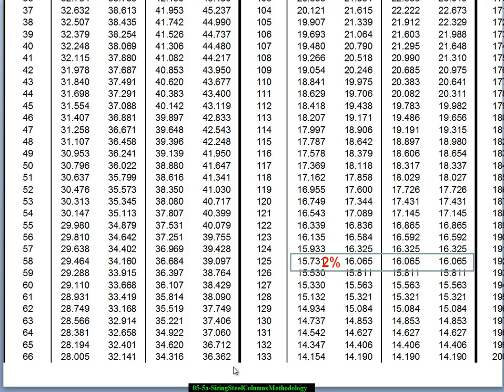The lower half of the table looks like the following. And the reason I'm jumping down to the lower half is I want to just go grab a number here. For a slenderness ratio of 125, so L over R is 125, we end up with a failure stress of 15.73 for the 35 KSI material. And then for all these other three grades, they just listed as 16.065. So the difference between that and that is only 2% or less. So what this is saying is when you get to a slenderness ratio of 125, from this point on all the grades are performing about the same. If you have a very slender column, you don't want to invest in a higher grade of steel because it's not buying you anything. Because the only important material property that's affecting the capacity of that column is the stiffness of the material. And all these grades of steel have the same stiffness.